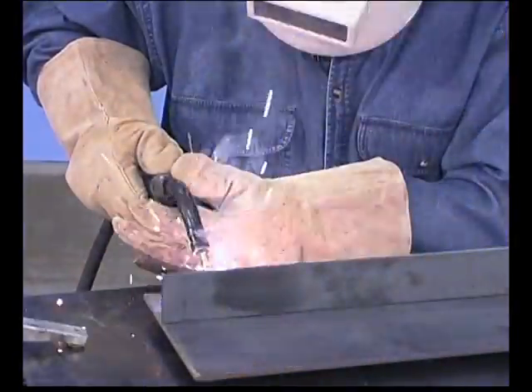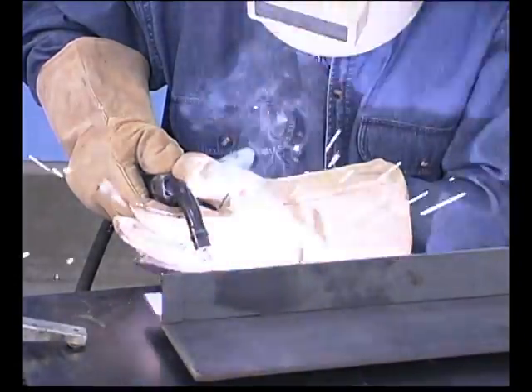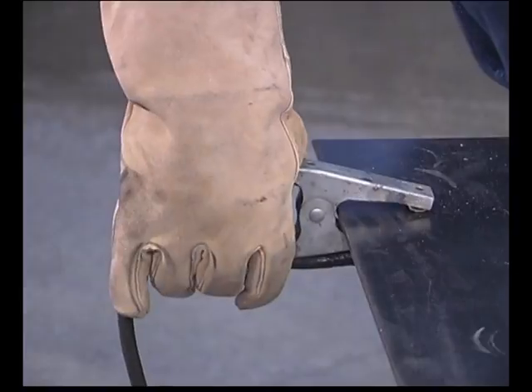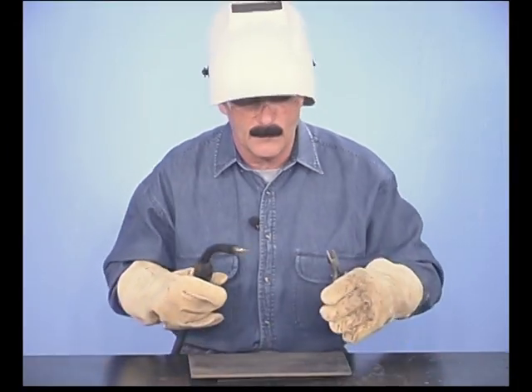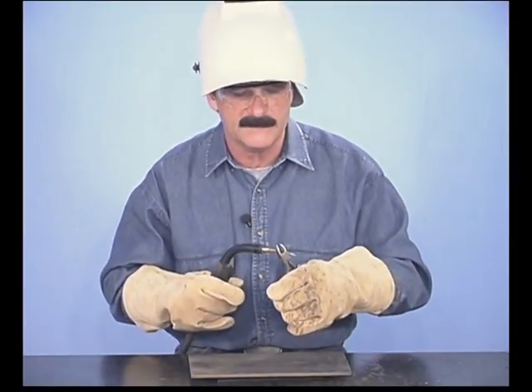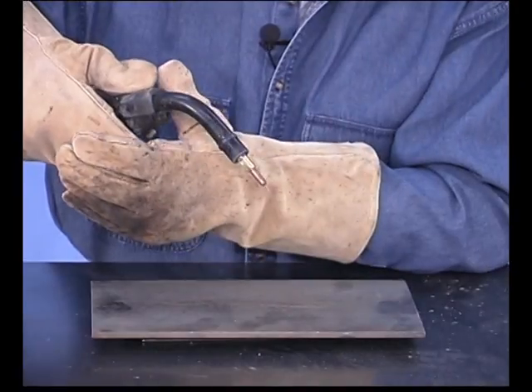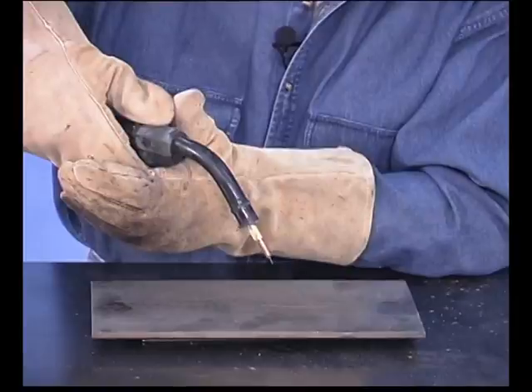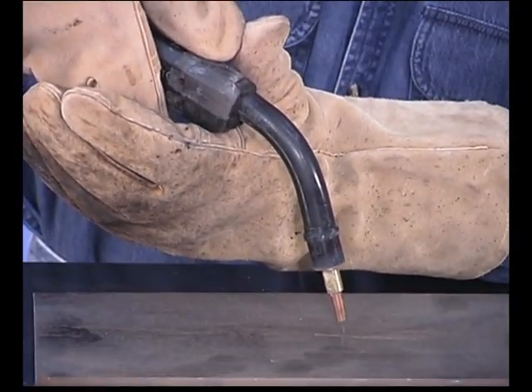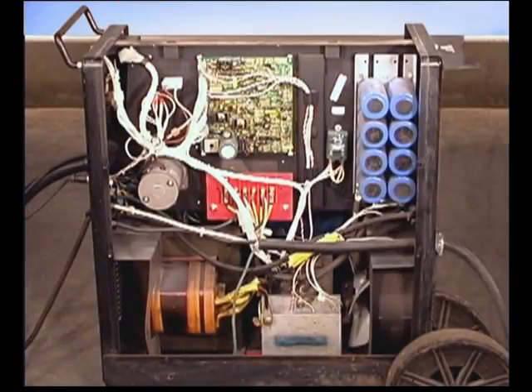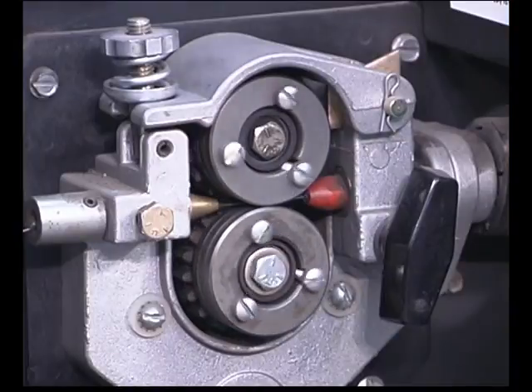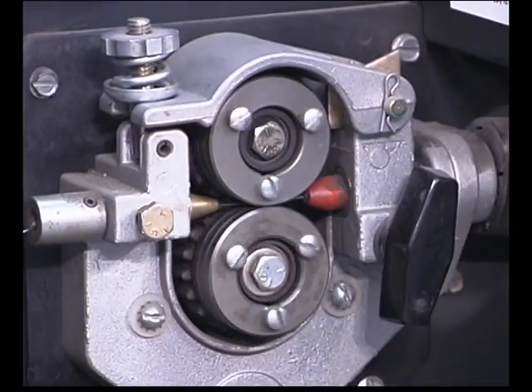If the wire sputters at the beginning of the weld and the arc seems like it doesn't want to start, check the ground connection. Trim the wire 1/4 to 3/8 of an inch from the end of the contact tip. Get comfortable and use both hands on the wire feed gun so you can be as steady as possible. When you pull the trigger, circuits in the power source provide current to the wire and the drive rolls start to feed wire. When the wire touches the metal, the arc is started.